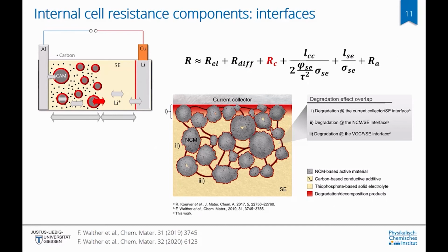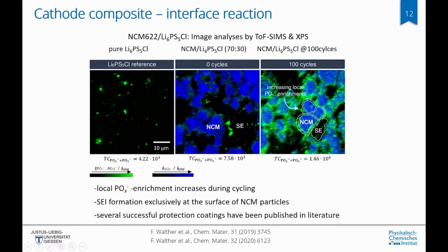Next, we'll have a look at the composite cathode, in particular the cathode interfaces, so the cathode active material interface with the solid electrolyte, because this is a place where degradation often occurs. And Felix Walter looked at the cathode composite in much detail and investigated the degradation at the current collector interface, the active material solid electrolyte interface, but also the carbon solid electrolyte interface can be degraded. With TOF-SIMS and XPS, he did a detailed analysis of these thiophosphate and NCM cathode composite before and after cycling.